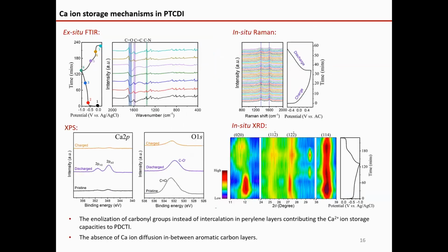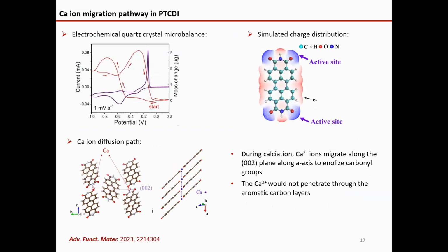So why is it so good? First, we need to understand where the calcium is stored. By FTIR and XPS, we found that the calcium ions are stored in the carbonyl groups. And by in situ Raman and XRD, we see there is no peak shift of the carbon layer. So that means there may be no insertion of the calcium ion between the carbon layers.